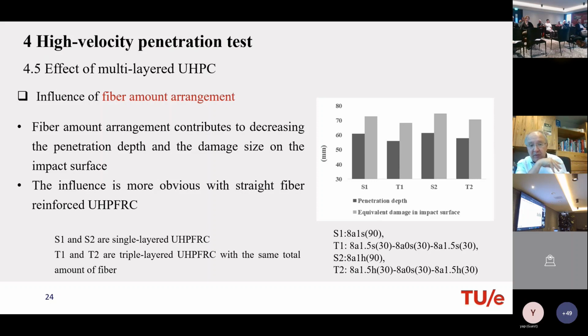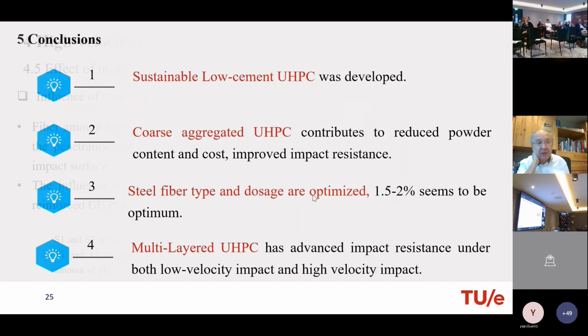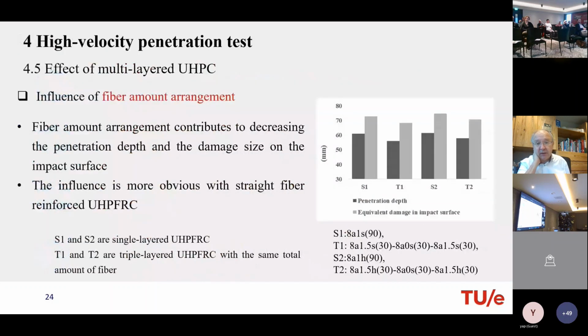Here we also have some results. Here we have single layer, again 90 millimeter, 8 millimeter maximum aggregate size. Here we have a triple system with 8, 1.5 steel, 0 steel in the middle, 30 millimeter, and then 1.5 in an outer layer. So the total steel content is the same, but now part is redistributed to the inner and the outer layers. And here again another recipe. And also there we saw that this is favorable.